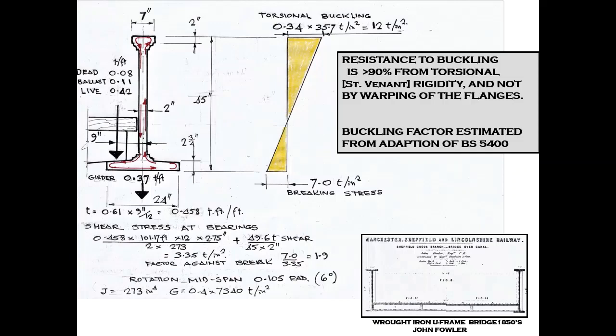It's not very clever. I've probably been a bit conservative, taking the eccentricity as 9 inches, because Simmons did show by doing tests on the girders which remained standing on the other track, he got end rotations somewhat less than my predicted figure here of 0.105 radians, or 6 degrees out of vertical, which is quite severe, and he got something less than half that, which probably shows that my assumption of the eccentricity of 9 inches is a bit over the top.